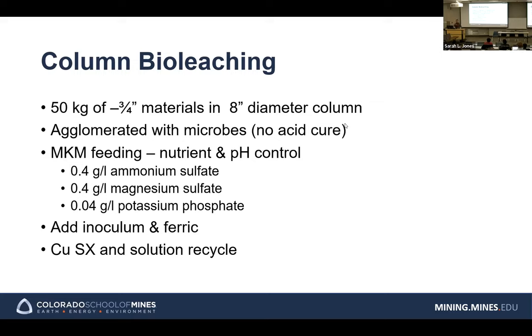So in column leaching, we can simulate the heap leaching operation in the lab. So using about 50 kilograms of 3/4 crushed material in a 6-inch or 8-inch diameter column. So we agglomerate with a nutrient solution, and add an inoculum of microorganisms, and ferric ion, and then we run that for a long time. I mean, how many months or how many years we run a heap leach, sometimes we run like 2 years or even 3 years. So in the lab, I also ran some of the columns more than 2 years.